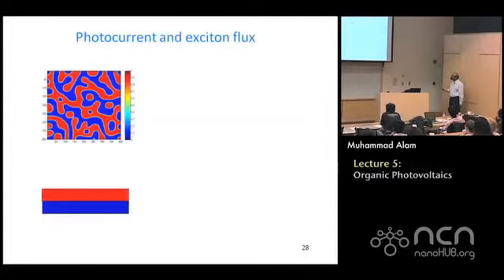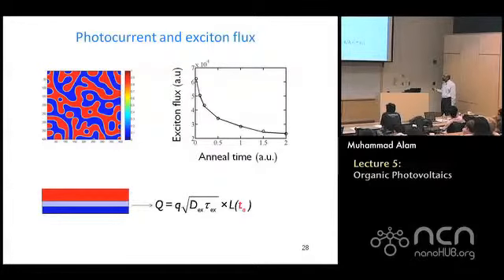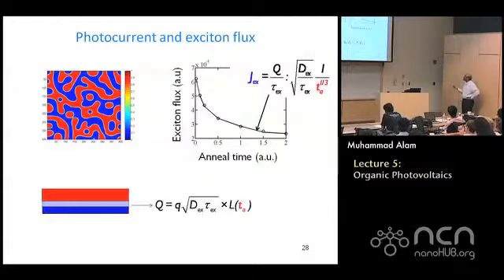Remember that only a fraction of the excitons that are generated can be dissociated, and those have to be within square root of D tau x. That is the part that gets dissociated. The rest of them essentially recombine and cannot be collected. So I can easily calculate what this Q is. This is the square root of D tau, this is how much it gets collected, and L is the interfacial area. So this will be the total charge that is collected. And if you wanted to calculate the exciton current, you do Q divided by tau x. That will be the total charge collected divided by the time it took to generate the charge. And from there you would say the exciton current would fall as anneal time to the power 1/3.